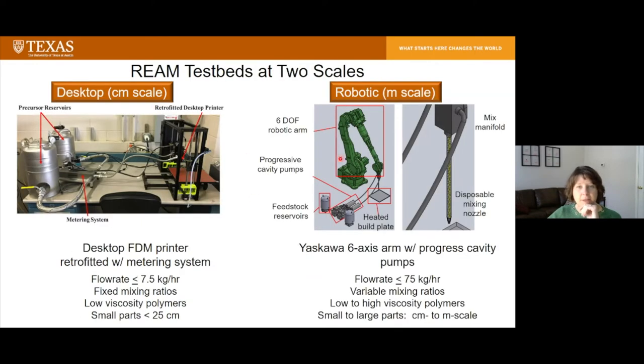All right, so here's a couple of the different systems that we've engineered. On the left-hand side, you can see our desktop system, which is basically a desktop FDM printer. It's a Lulzbot TAZ 6 in this case, that's been retrofitted with a metering system that you can see on the left. Flow rates up to around 7 kilograms per hour. So this is at least an order of magnitude faster than almost any smaller scale FDM printer that's available. It can build small parts up to about 25 centimeters or so, 10 to 12 inches, and low viscosity polymers simply because of the pumping system.